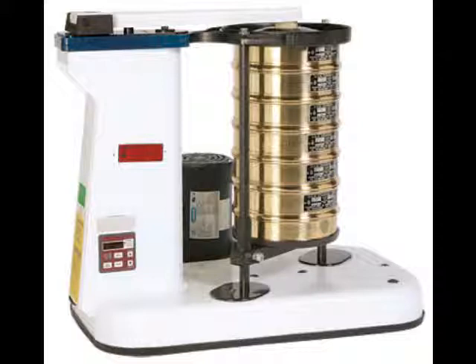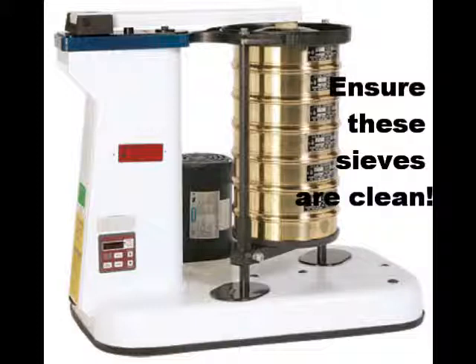A couple things with the sieve analysis that you want to be sure of, whatever lab you use. You want to make sure that the lab is clean and practices good old laboratory meticulousness. What I mean there, the screens are capturing the sand particles. So, it's common for the screens to hold sand particles even after the test is done. You want to make sure that the lab is religiously cleaning those test sieves after each use and before they ever put your sand in it. Because someone else's sand particles could contaminate your results and jack up the whole thing.